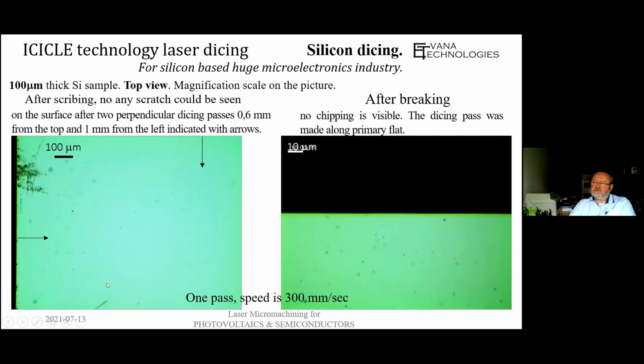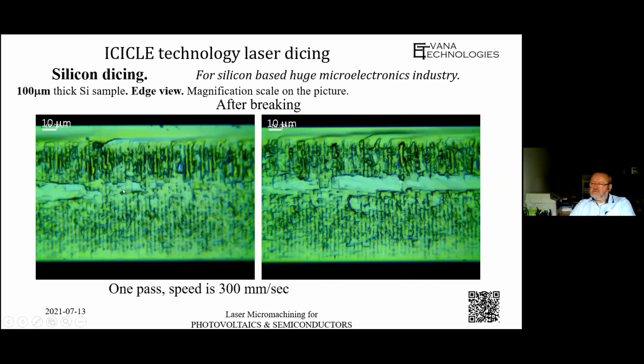Here you can see examples for 100 micrometers thickness silicon. You can see the line direction shown by arrows, and on the top surface you don't have any damage after dicing, and after breaking you can see a very straight line without any cracking, chipping, etc. Here is the cross section of this material after breaking, 100 microns, and this is almost zero cracking of the material. It means zero curve cleaving of the material.